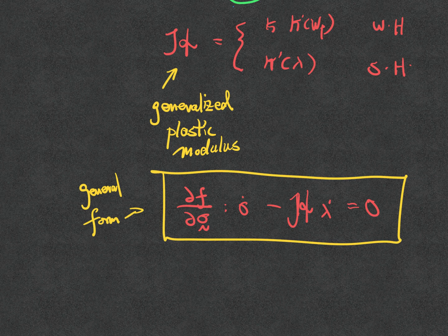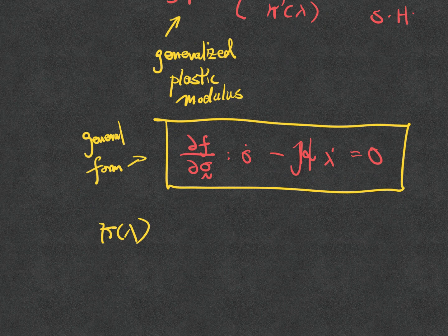So in practice, how does it work? How do we actually define the hardening law? In practice, we need to determine what these functions are. People have been using polynomials to do it, have been trying curve fitting with exponential components, and have used symbolic regression to obtain it. You can see a paper from Los Alamos a couple years back that used symbolic regression to do it.